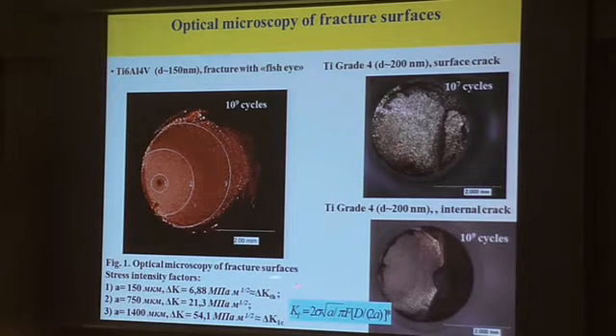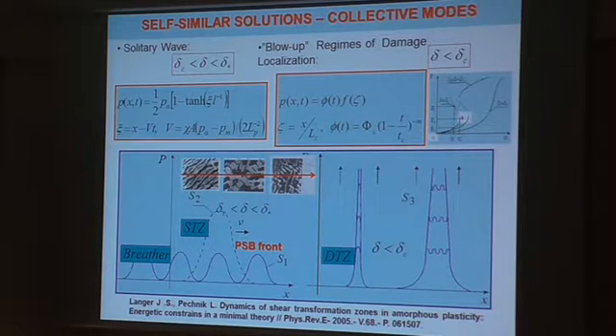We investigated for very high cycle, for gigacycle fatigue, the morphology of titanium samples with fine grains for the stability. And of course, we revealed characteristic pattern related to fisheye, FGA area, and the area of crack propagation. And since we discovered similar solutions for kinetics of crack initiation and crack propagation area, we decided to establish the links between self-similarity in characteristic solution that was established theoretically and a real scenario and real morphology in terms of the scaling characteristics.